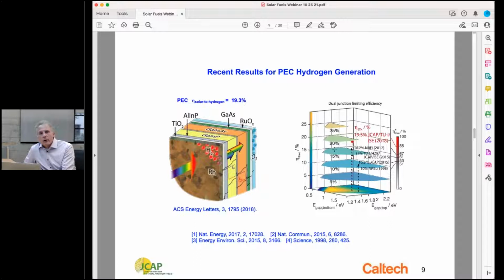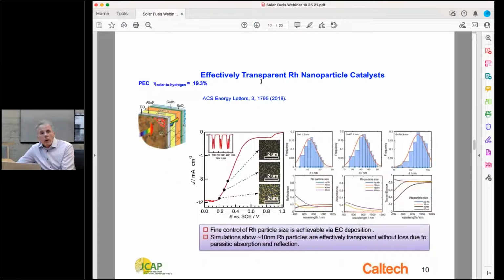Between 2015 and 2020, we saw a rapid rise in the record efficiencies for photoelectrochemical water splitting, and this device achieved a solar-to-hydrogen efficiency of 19.3%. So how did it do it? It began with the use of rhodium nanoparticles, which were produced by electrochemical deposition.